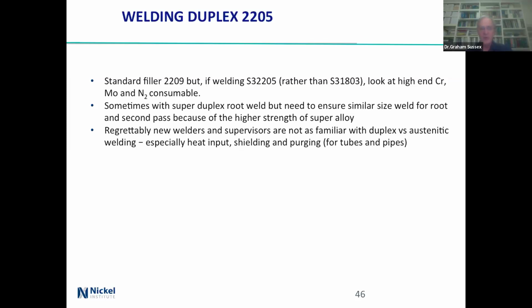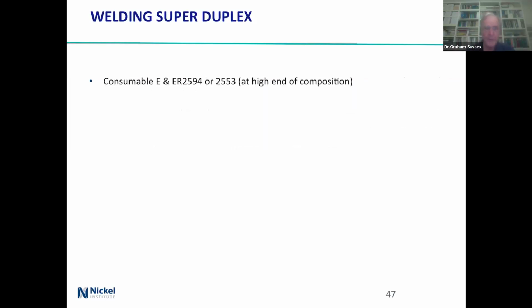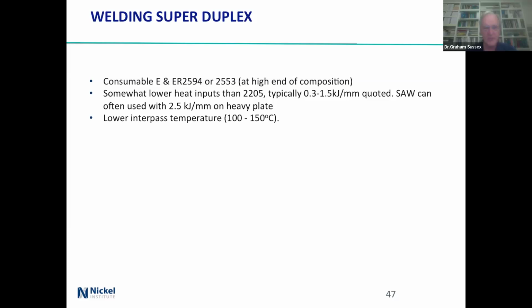And unfortunately, new welders and supervisors may not be as familiar with duplex. People typically go carbon to austenitic to duplex, and are particularly worried about heat input, shielding and purging, if you're talking about tubes and pipes. Welding super duplex, use the high end of composition, because you're looking at something going into a very aggressive environment and you're going to lose some of the consumable at the actual welding process.